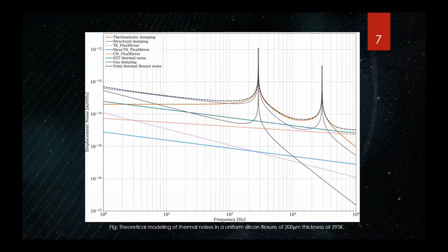So this is the noise budget. It highlights some of the sources that are critical for us. The main thing to look at is this dashed line, and this is the noise budget for 300 Kelvin and a 200 micron thickness flexure. And the dashed line over here is the total noise for the experiment. And you can see it's sitting at a level of 10^-15 meters per root hertz. And I'd like to highlight that this is small and you need isolation to measure this.